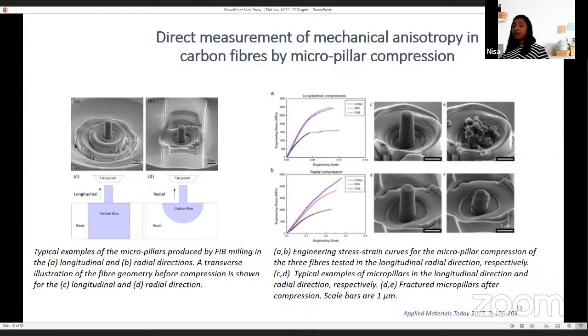So to address these issues, we come up with an approach. It's a very simple and direct method to measure the transverse and longitudinal properties of carbon fibers through micropillar compression. So here is a typical example of the micropillars made by focused ion beam milling, both in longitudinal and radial directions. So here are the fractured micropillars after the compression.